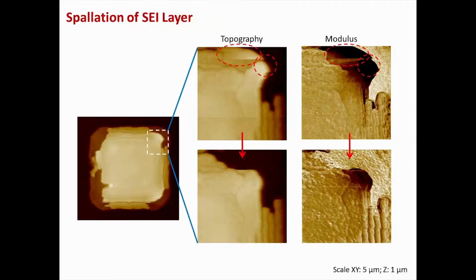So what happens after you keep cycling further and further these islands? One thing that is happening is that once you have already cracked and partially delaminated the SEI layer from the underlying silicon, due to cycling fatigue, it can also spall off. And that is what we can see here: part of the SEI from the underlying silicon has already spalled off, and only the center part, which is not going through any tensile strain, remains there as it is.